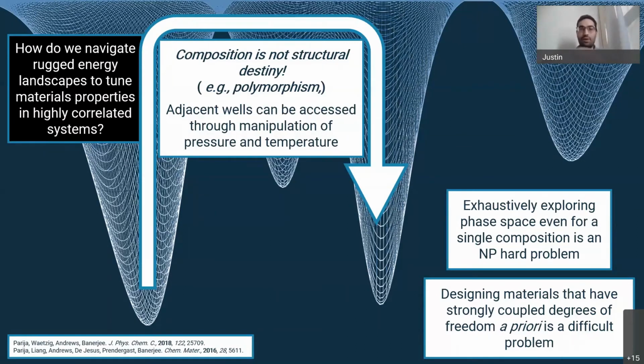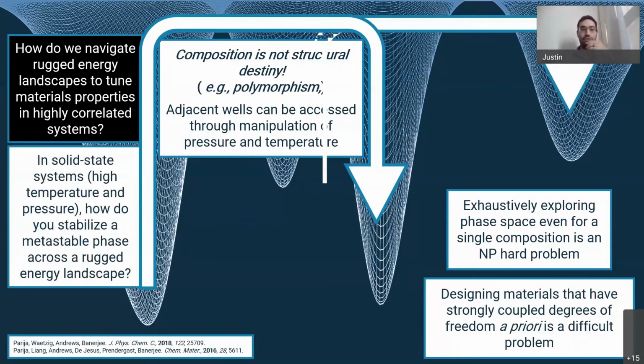But despite the difficulty of this issue, it's important to remember that composition is not structural destiny. And so we can start to look at polymorphs of different materials because that gives us different connectivity and can profoundly influence the electronic and the ionic diffusion in solid-state materials for energy storage.